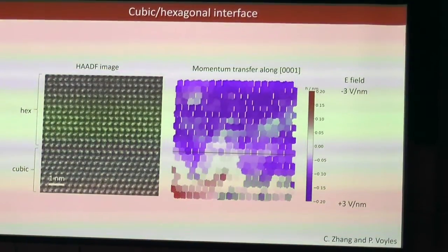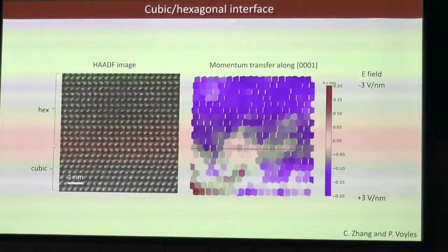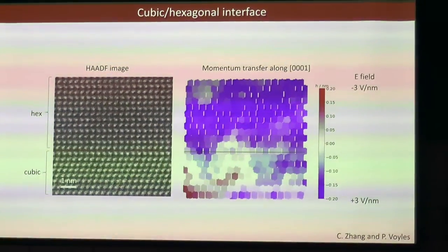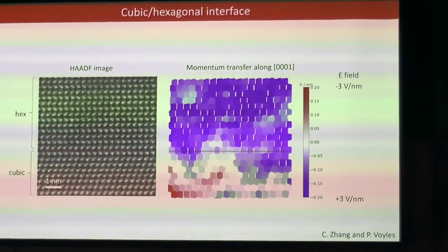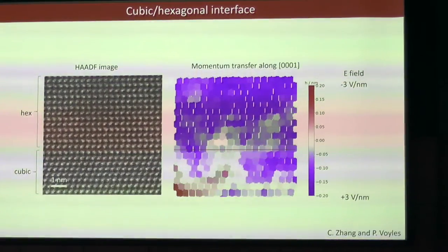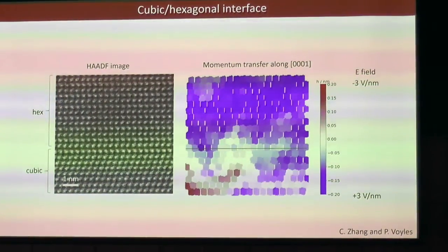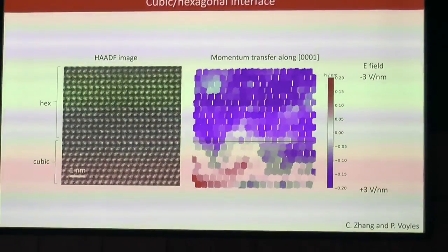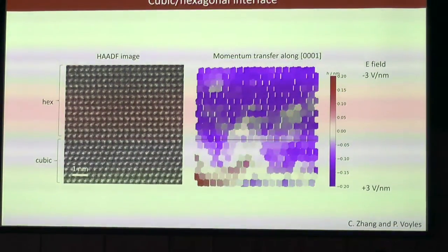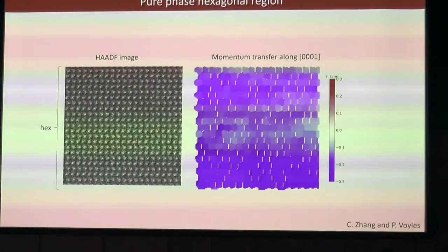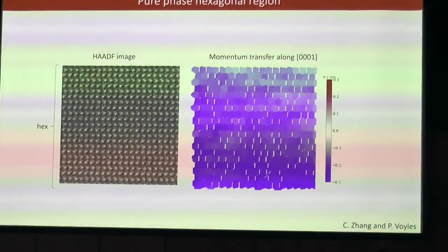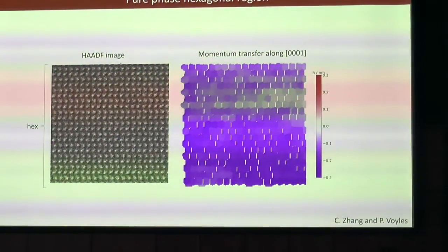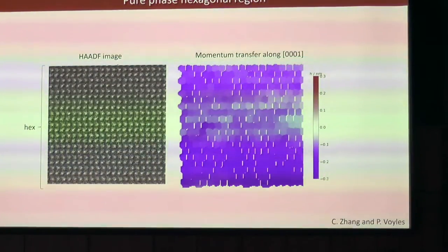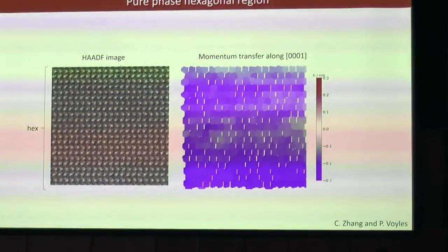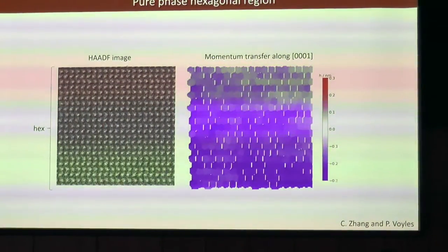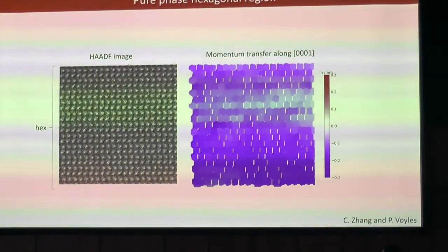Okay? And what we see is that in this cubic region where there's no unique polar axis, we see a mix of positive and negative momentum transfers, right? But in this hexagonal region, we see a uniform direction of momentum transfer. So that's all well and good, what we expect. We can do a similar measurement on a pure phase hexagonal region, and we see monodirectional momentum transfers. We're still looking around. We still haven't seen any obvious evidence for a domain wall yet, but this is still very early stage.